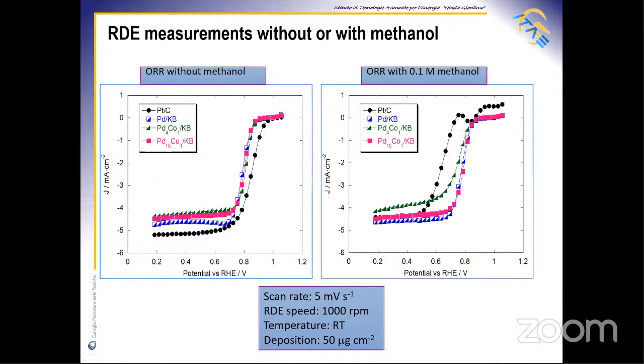Platinum on carbon is the more active electrocatalyst in the bare electrolyte, but in the presence of 0.1 molar methanol solution, palladium on Ketjenblack is the most active, with the most positive onset potential and the largest limiting current density compared to that obtained with the platinum on carbon. These results show the better tolerance to low methanol poisoning of palladium-based catalysts compared to a benchmark platinum catalyst.